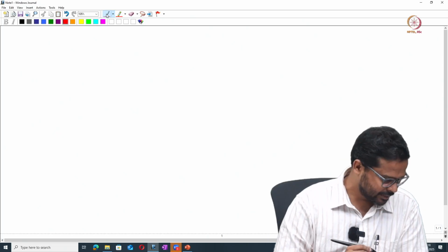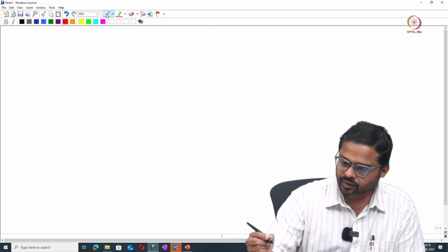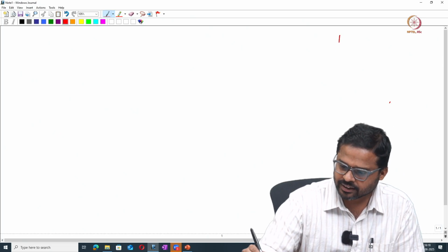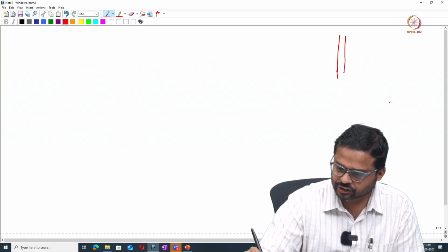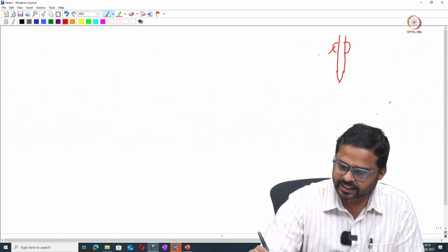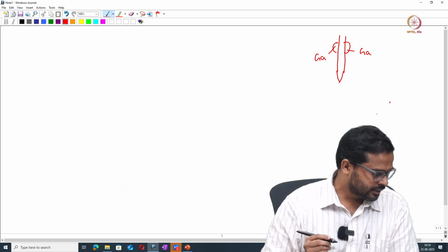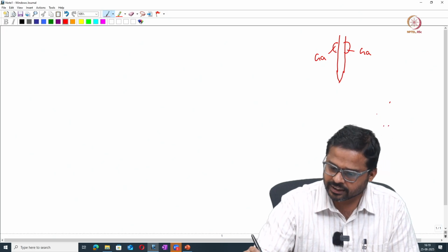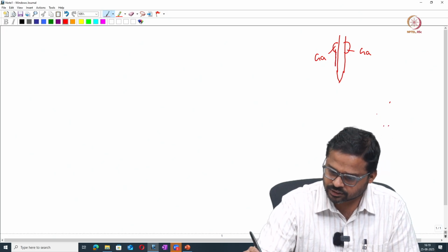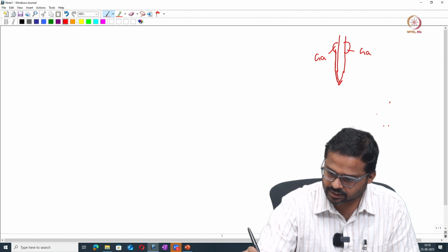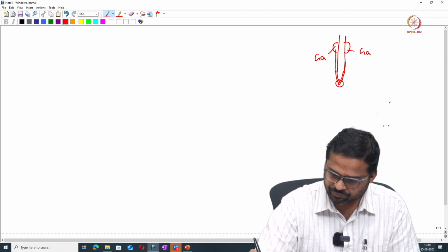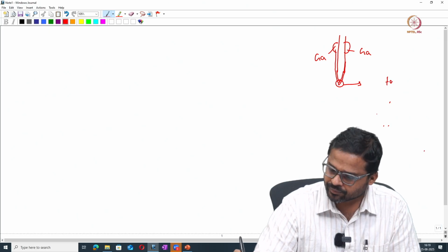We started with the gun source. As I have told that time, in the gun source you usually have a sharp tungsten needle, and there is a reservoir, a gallium reservoir. From this gallium reservoir, the liquid gallium flows to the tungsten tip and forms a Taylor cone,